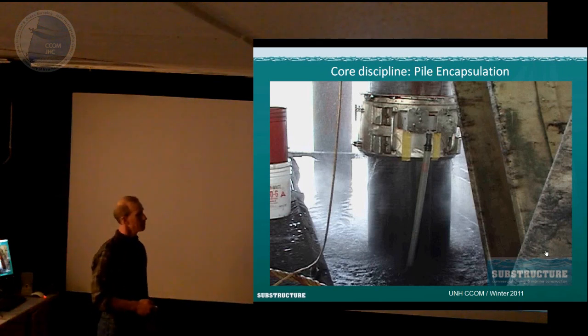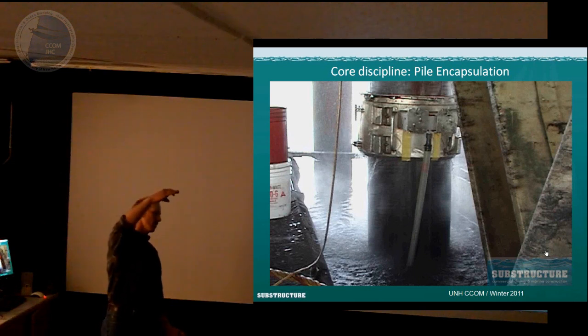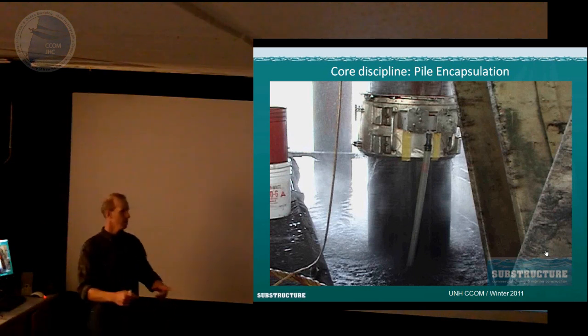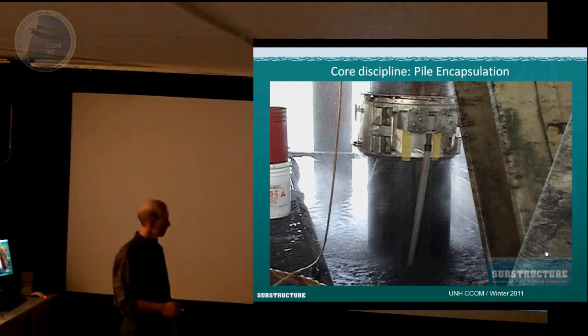So you start at the bottom and you seal it? It all depends on the particular application. For deeper piles, we normally incorporate a cathodic protection system once you get down below the oxygenated area. So you'll go 5 or 8 feet below low water. So that gets you out of the highly oxygenated area where we're going to have oxidation, corrosion, rust, and then we'll go right well above the intertidal zone and end up with some pretty nice results.